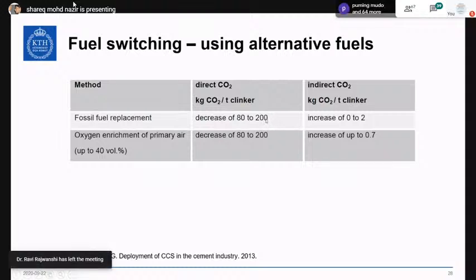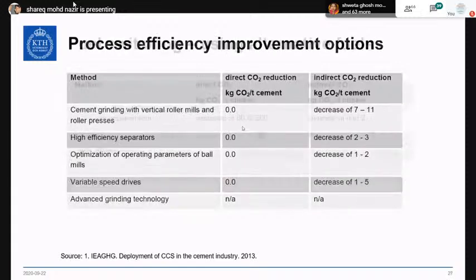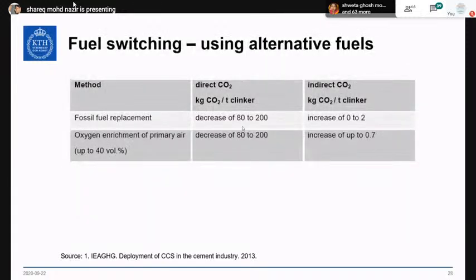kg CO2 per ton clinker, and as we discussed, the oxygen enrichment might help. But when we speak about fossil fuel replacement with biomass, we are able to decrease the CO2 because the CO2 emitted from biogenic sources is considered neutral in the atmosphere. So yet again, if we start implementing all these options, we would still find it difficult to reach the 700 to 800 kgs per ton clinker target that we need to reduce, that we need to decarbonize in the cement plant.